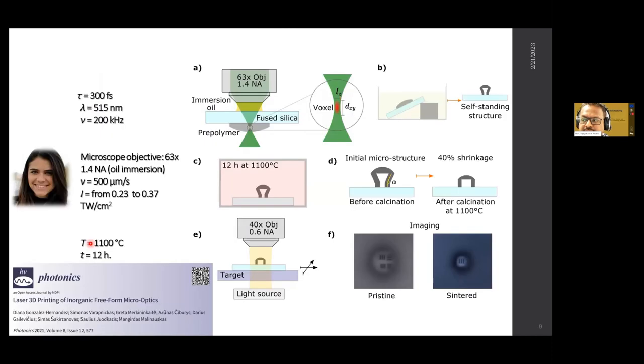So it's downscaling, but we can predict it and pre-compensate, for lenses, so that the lens is not deformed, it's just shrunk. If we would make straight legs, they would be bent. So we need to allow the shrinkage to occur. Otherwise, it will depend on the substrate.